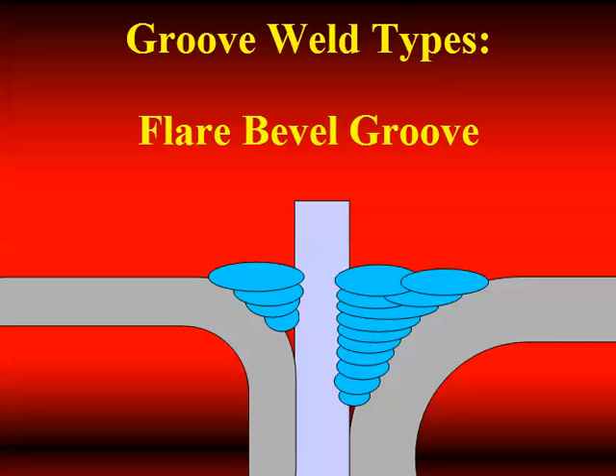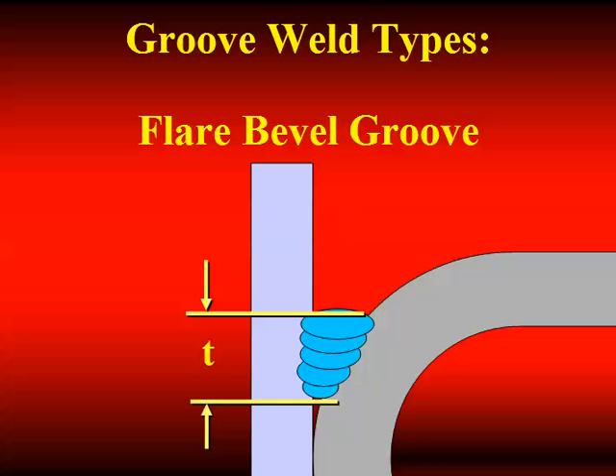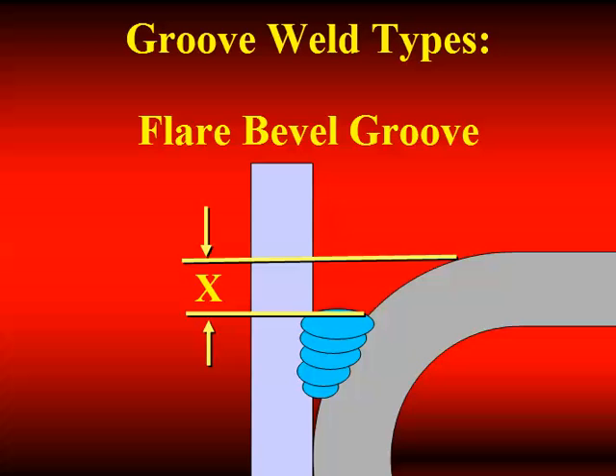So now we have provisions in the AISC specification for underfilling the joint. And in this case, you specify the thickness of the throat that you need, and the actual means by which this is implemented is you measure the unwelded portion off of the face. Now, this reduces some cost, reduces some distortion, and unless there's some kind of aesthetic requirement that says you fill it, you don't have to. If you do have one of those requirements you have to fill it, there's other materials like Bondo that are better than weld metal to fill those things out.